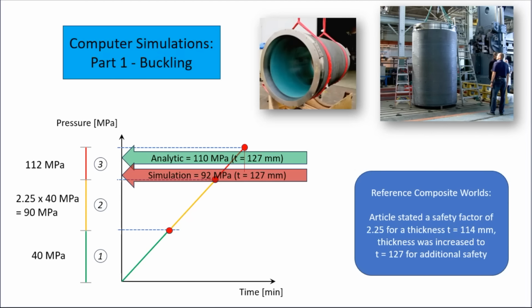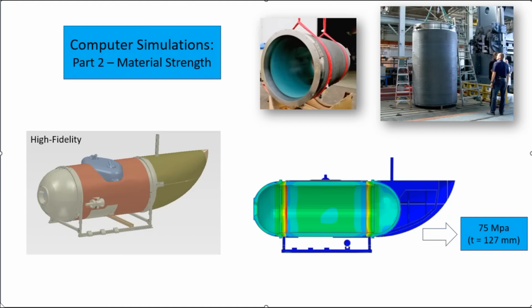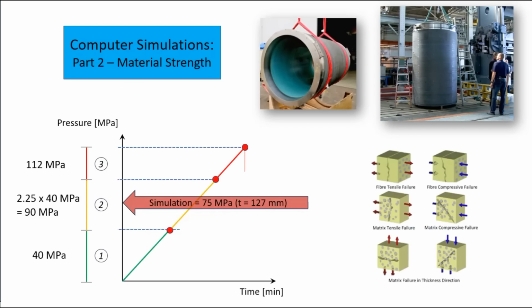The second part of the simulation involves material strength. In the case of CFRP, we consider fiber as well as matrix fracture in tension and compression. Using this methodology, we get a design load of about 75 megapascals. If we consider imperfections as a third aspect, the design load is reduced even further. The well-known energy barrier criterion, EBC, delivers a design load of 56 megapascals.